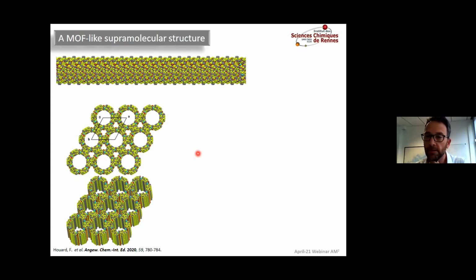This is heptane. We have heptane inside. And we tried with other solvents to see if we can tune the cavity and so on, and we are not able to have crystals. Maybe it's a question of affinity between the chains that have a C6 with the heptane, and that match well to stabilize the structure. But as soon as we change to other solvents, even aliphatic solvents, we were not able to have other crystals. Okay, very nice. Other questions?